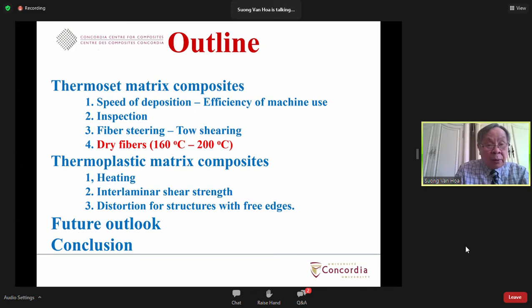Now, the last thing I will talk about for thermoset composites is dry fibers. The reason I put dry fiber within thermoset composites is that when we do the automation with dry fiber, we make only the preform. After you have the preform, you need to infuse resin into it to make the composite, and normally people use a thermoset matrix as the resin. With dry fibers, normally they have to use some kind of thermoplastic binder. During the process, the binder needs to be melted so that you can place the fiber. As such, you need a good amount of heat. The temperature is between 160 to 200 degrees centigrade to process it.